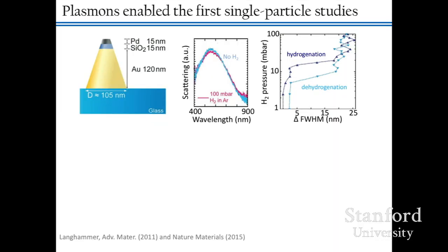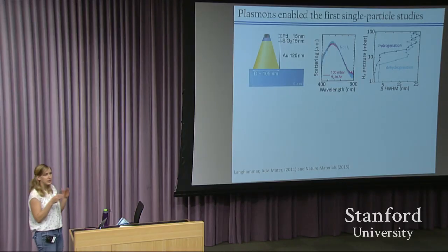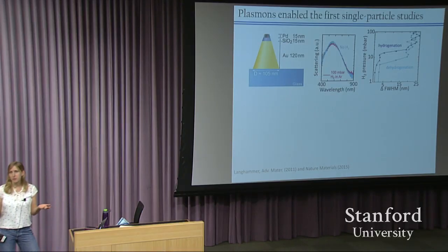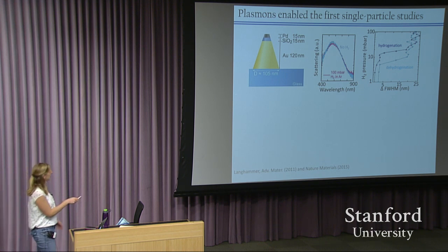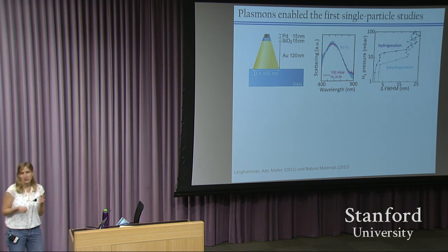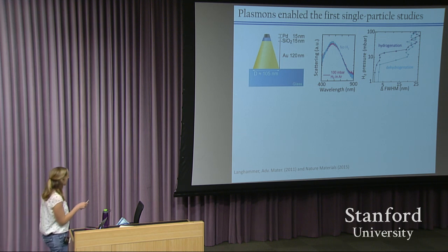So researchers turned to single particle studies, and plasmons enabled the first single particle study starting in 2011. There was first this really nice study by the Langhammer group at Chalmers University, where they put small palladium nanoparticles on top of a gold nano antenna, and then used optical scattering and spectroscopy to detect what the phase of the palladium would be. If you just had the palladium on its own, a single particle wouldn't quite scatter strongly enough to figure out what the phase would be. But by having this gold nano antenna, they could get a pretty significant scattering signal.